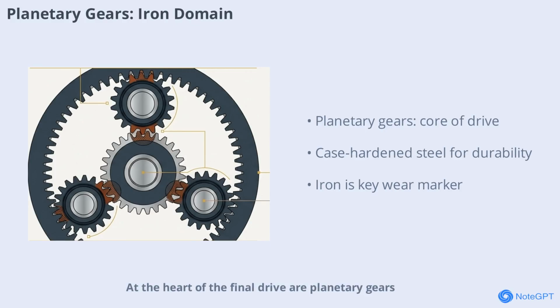component life. At the heart of the final drive are planetary gears, engineered for continuous heavy load. These gears are made from case-hardened steels with a tough core and a surface hardness of HRC 58-62. This design ensures durability under stress but also makes them the primary source of iron, Fe, in oil analysis. When wear occurs, iron particles are released, providing a clear diagnostic signal. Knowing the alloy composition, such as SAE 8620 with nearly 97% iron, helps us interpret oil analysis data and distinguish between normal and abnormal wear.